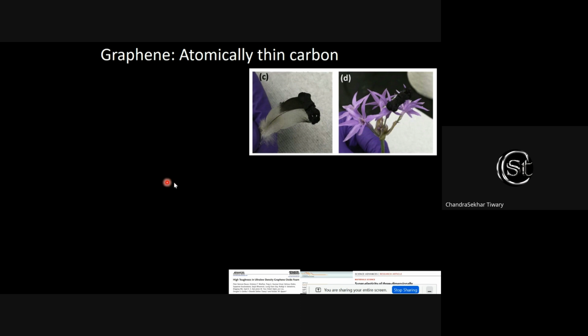But our initiative or our understanding was more in terms of structural application of graphene. And the question we asked was, what does graphene have to offer us in terms of structural material. The first part of graphene is that you can exfoliate them, and you can see this black block here or here. If you see graphene, you can put them together. First, take graphite, exfoliate it, make single or a couple of layers of carbon. Then put them together with the right chemistry and right processing conditions. You can make a foam structure.